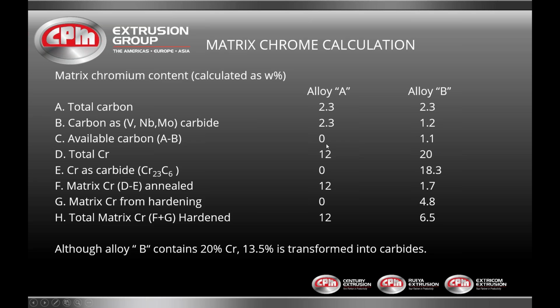The available carbon for A and B: alloy A is 0, alloy B is 1.1, and so on down the line. Although alloy B has 20% more chrome, 13.5% of it is transformed into carbides, so therefore you'll have a lot less corrosion resistance.